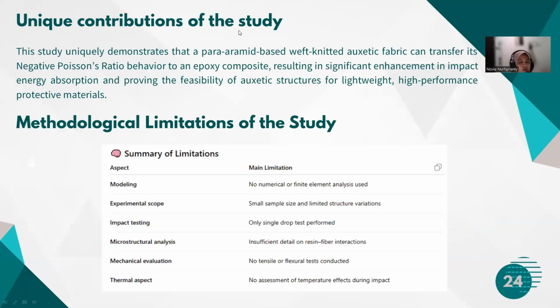Unique contribution of the study. This study uniquely demonstrates that a para-aramid-based weft-knit auxetic fabric can transfer its negative Poisson's ratio behavior to an epoxy composite, resulting in significant enhancement in impact energy absorption and proving the feasibility of auxetic structures for lightweight, high-performance protective materials.